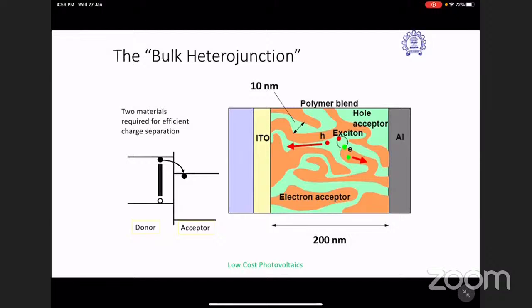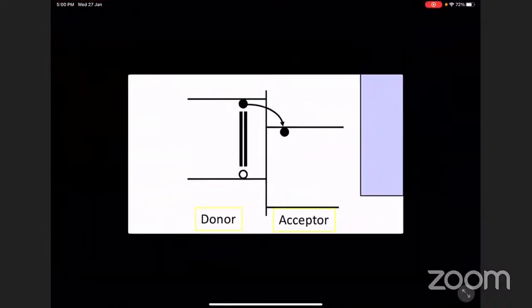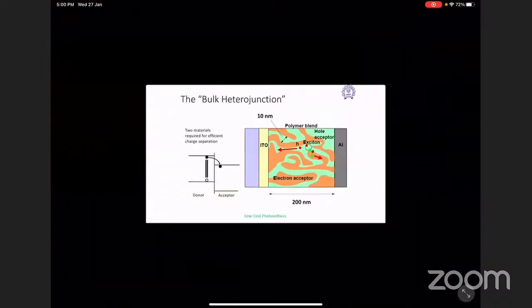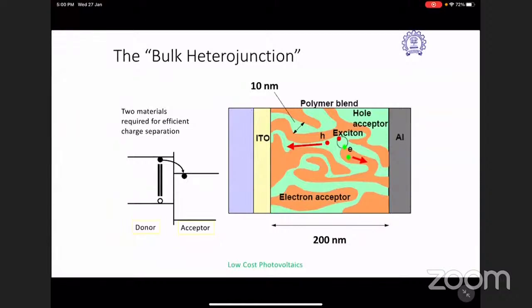If they become too close, then that is not useful, because then you are going to lose lots of energy when the electron gets transferred, because your energy is getting absorbed by either of the materials. You don't have very good absorption strength where you can directly transfer the electron from the HOMO of the donor to the LUMO of the acceptor. But you will always be absorbing directly within the donor or within the acceptor. And then you do the charge transfer, then you are going to lose lots of energy if you have more energy offset. Okay, thank you.